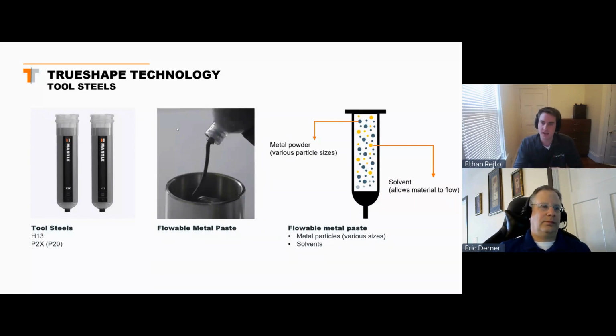It's flowable, and inside of that paste is a combination of metal powder, various different particle sizes, mixed with some solvents. Those solvents allow the material to flow so it can be extruded through a nozzle. It also fully entraps all of our metal powder, so at no point are you exposed to any loose metal powder during the process, which is something when we're talking about ease of use and accessibility. Obviously, there's some barriers that come with that. So the ability to have a fully encapsulated metal powder is another benefit of our paste process.